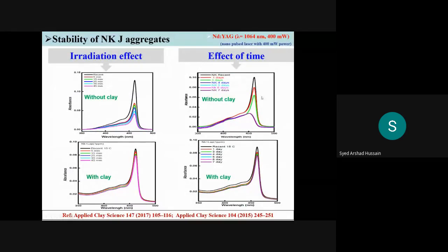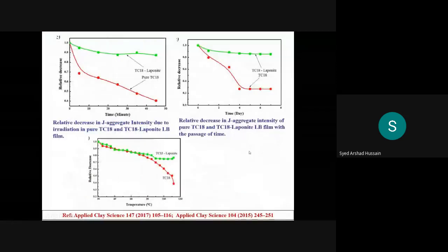So this is the optical behavior of J aggregates. J aggregates mainly show red-shifted bands, very sharp, with almost zero Stokes shift. These are some characteristics. For nonlinear optical activity, we use an Nd:YAG laser, wavelength 1064 nm, with power of the order of 400 milliwatt. What we did, first we exposed this J aggregate under this laser, and we saw how the stability behaves, because in an LB system the stability is sometimes very low, because it is based mainly on electrostatics and van der Waals interactions. What you can see, this green one is the stability of the system measured with time without exposure. But when we expose, you see the red line decreases. This is for a single layer. Then again, we did it for 10 layers.